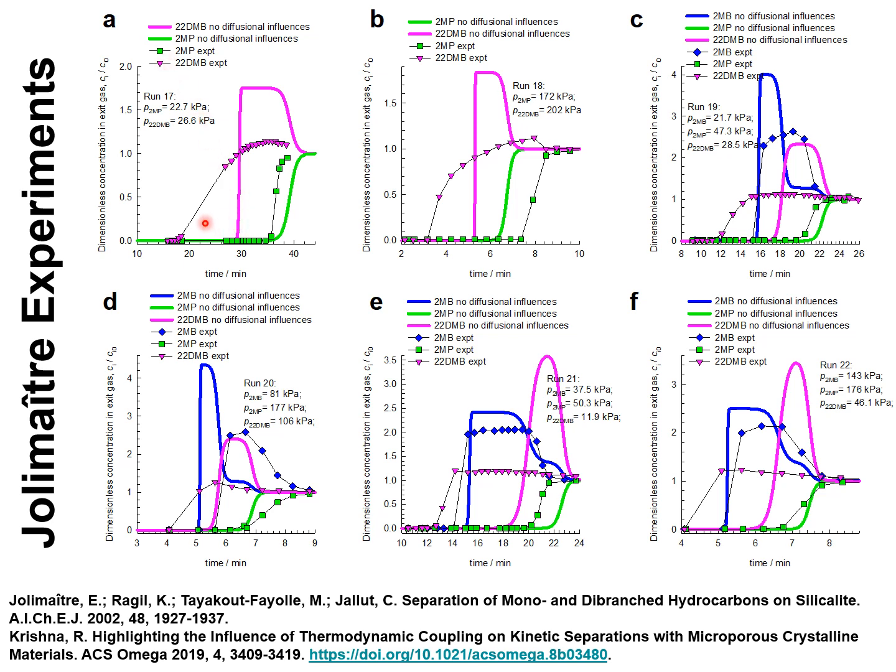The experiments show that the component to elute first is 2,2-dimethyl butane that has the lower adsorption strength and also the lower intra-crystalline diffusivity as compared to 2-methyl pentane that has a higher adsorption strength and also a higher diffusion coefficient.